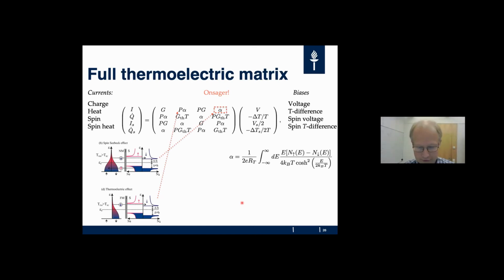I presented earlier a coupling between charge and heat current, but in fact you can extend this response matrix by not only describing charge and heat, but also spin and spin heat. Then you get a 4x4 matrix, which is actually full, and only depends on four quantities: the conductance, thermal conductance, spin polarization, and this alpha, which describes the spin dependence of the density of states.